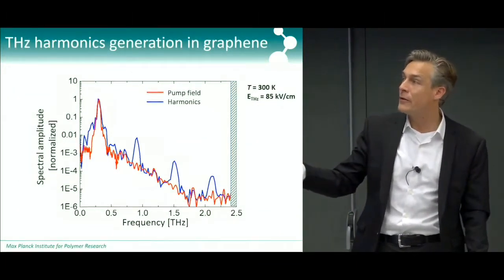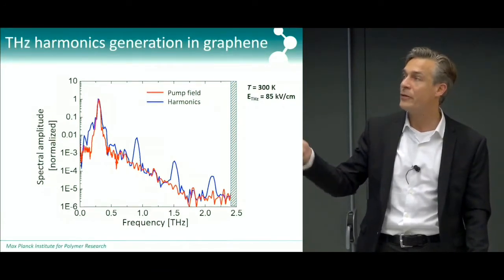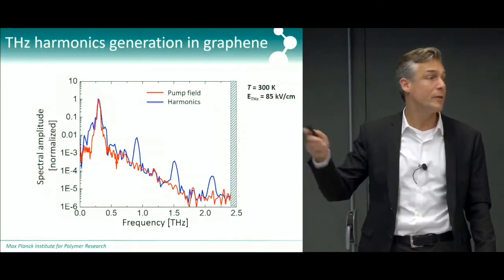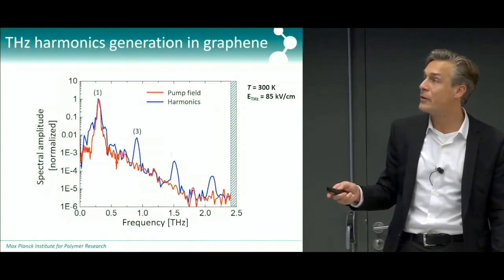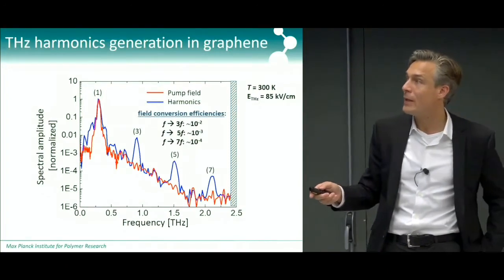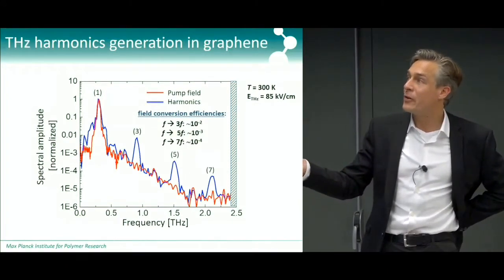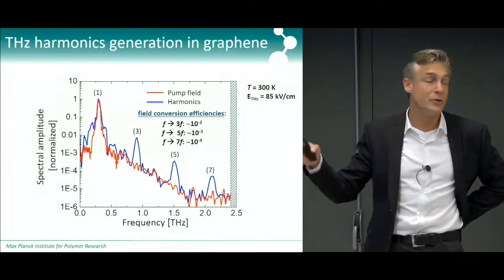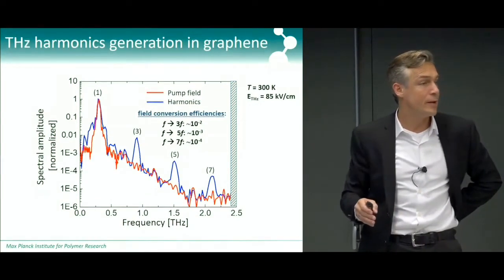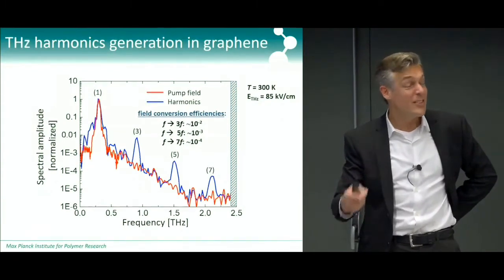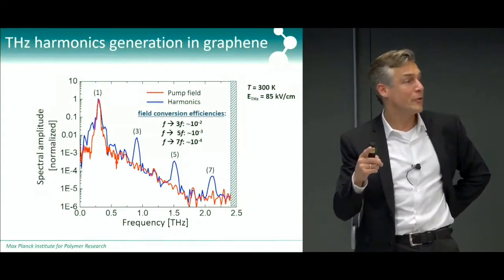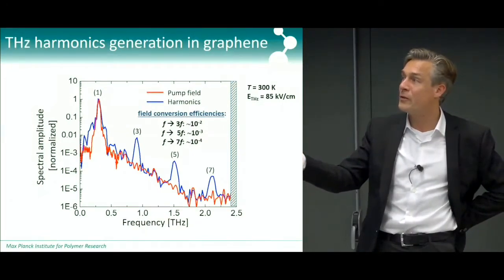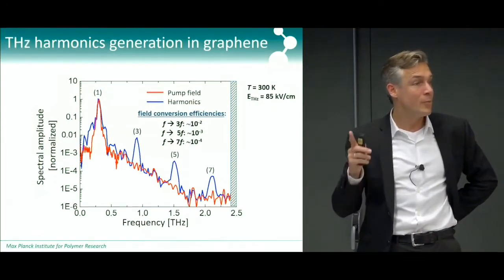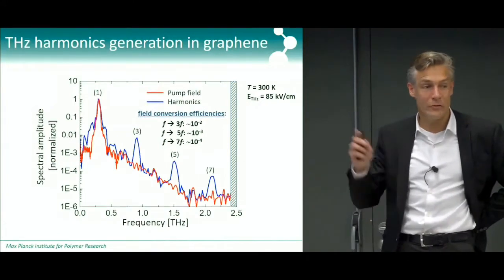In red you see the excitation pulse, and then in blue you see these different harmonics, so the third, the fifth, and the seventh harmonic of the terahertz being generated. And you see that we get field conversion efficiencies of percent in this way. And again, I can't stress this enough, this is a single layer of material. So we get a conversion of 1% of the field from the fundamental to the third harmonic in one layer of material. This is quite high.